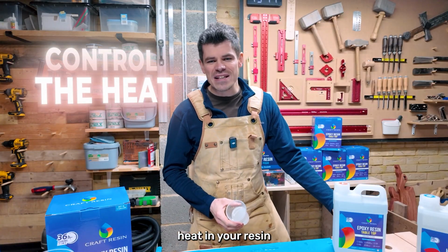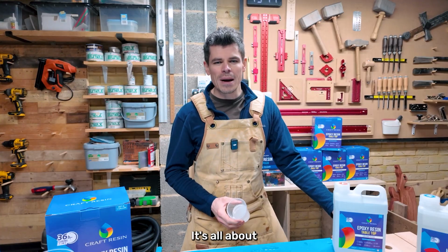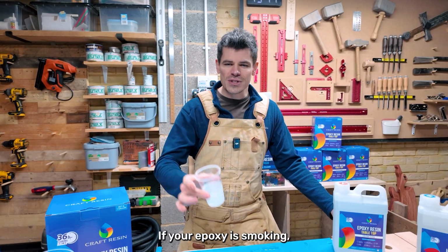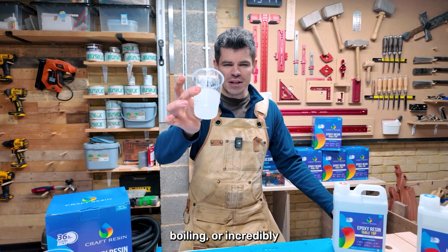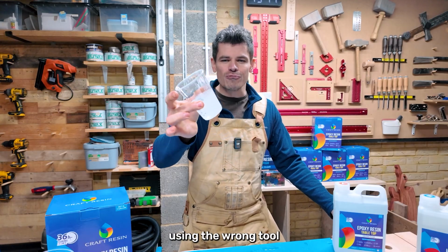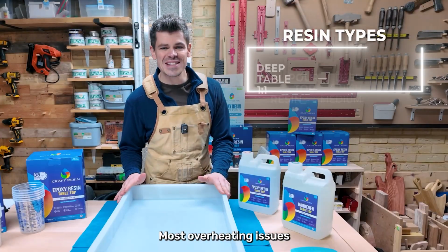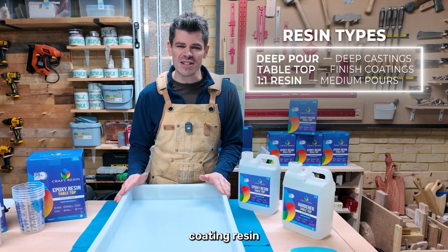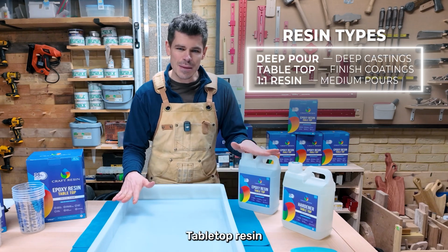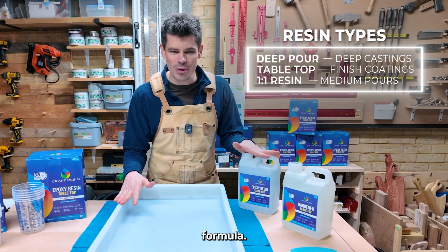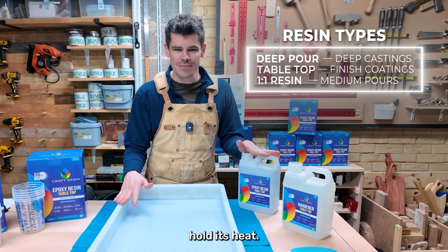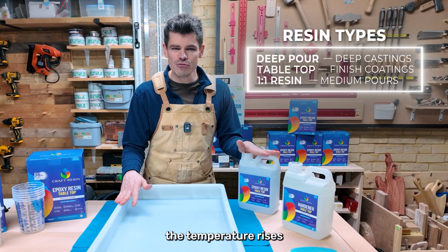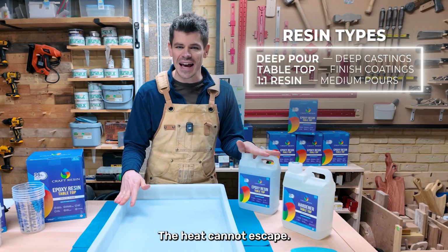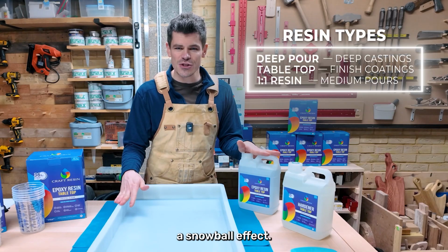Controlling the heat in your resin is simpler than you think. It's all about managing the chemistry. If your epoxy is smoking, boiling, or incredibly cloudy, you are likely using the wrong tool for the job. Most overheating issues happen when you use a coating resin for deep casting. Tabletop resin is a high viscosity formula. It's designed to hold its heat. If you pour it too thick, the temperature rises way too fast. The heat cannot escape.